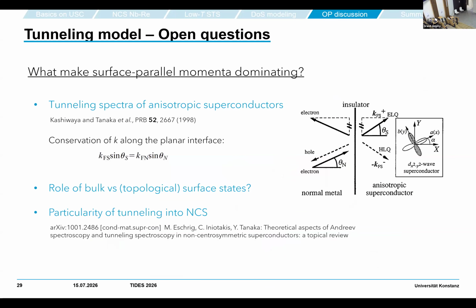This model has been put forward for planar junctions, to explain that if you have a Fermi surface mismatch, the directional angle could be spread. Here we also have the situation that the Fermi energy of platinum iridium is much larger than that of niobium, so we have two different diameters of the Fermi surface. This could explain why, instead of the usual Tersoff modeling directional to the current, we'd spread the cone - and this is well established in theory. But it does not explain why we have a preference for the in-plane moments. This is still something we would love to understand.